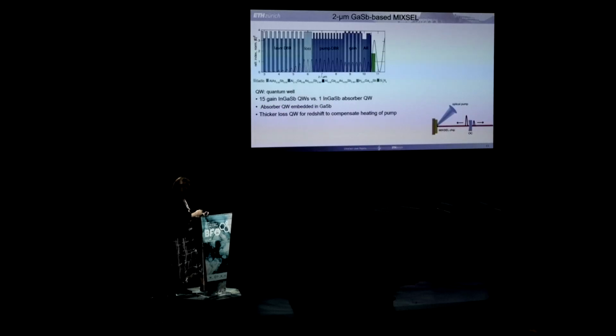And over time, we then successfully demonstrated also the MIXSEL in the gallium antimonide system operating at a center wavelength of 2 micron. So you have an AR-coated section, then you have like 15 indium gallium antimonide quantum wells, then a pump DBR, and then an indium gallium antimonide absorber layer here. And this is then on top of a high reflector for the laser wavelengths, right? And as you can see, the field enhancement is a little bit higher in the absorber than in the gain.